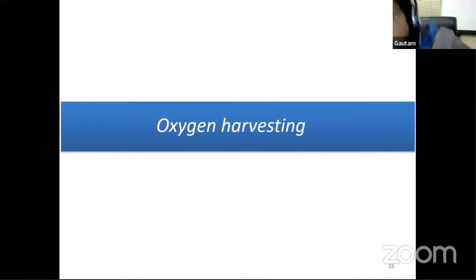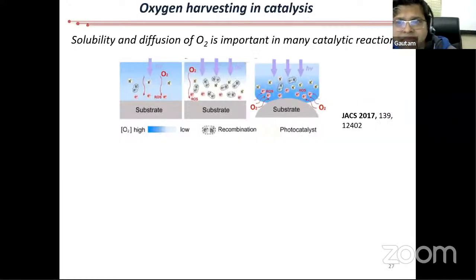So let's come to the first interesting property, oxygen harvesting. Now, oxygen harvesting is something very important because when you do oxidation reactions, and as we discussed, we make carbon dots to do some reactions. And if you want to do oxidation reactions, as we discussed, it's not good to use the conventional oxidizing agents. But why can people not use free air for doing oxidation reactions? One of the reasons is that oxygen solubility in water is very poor. And oxygen diffusion is also very poor.